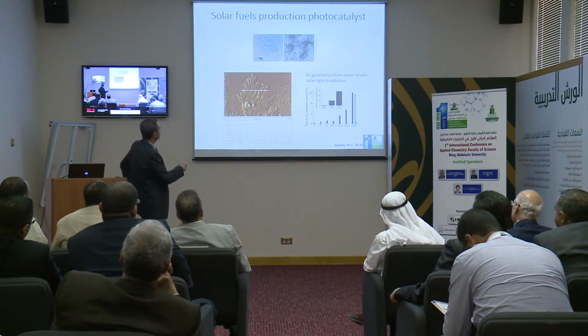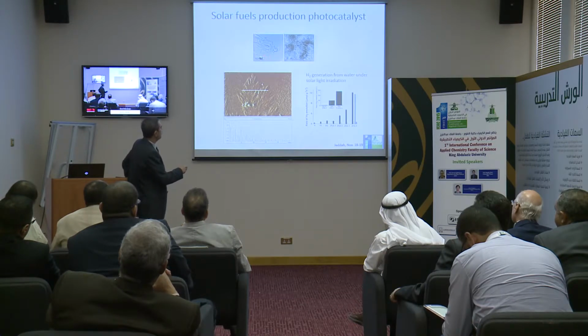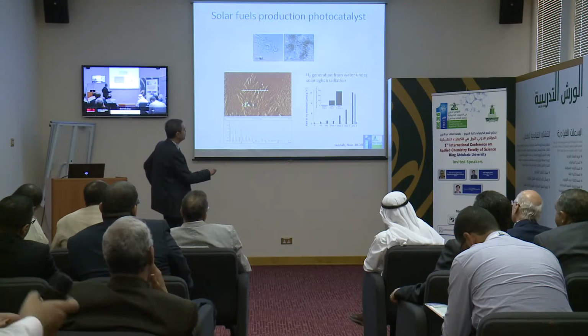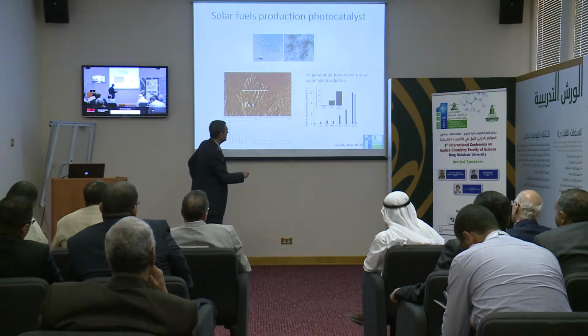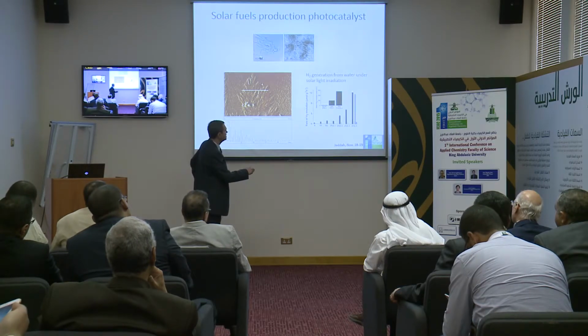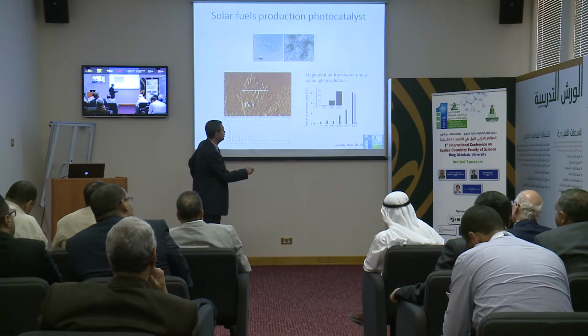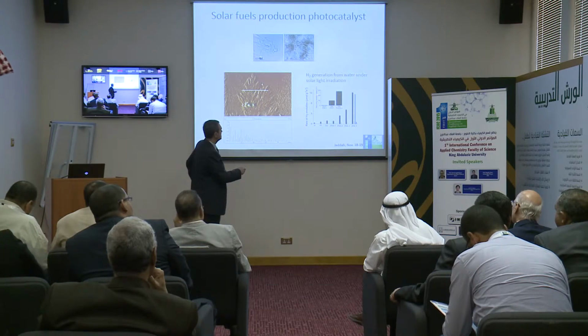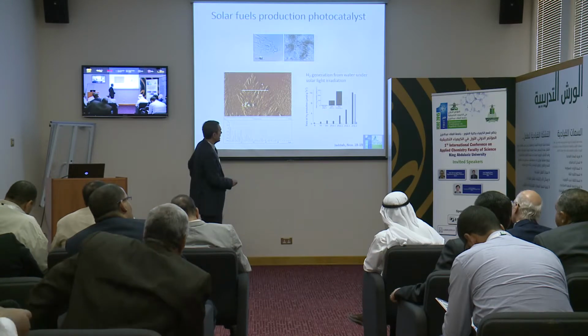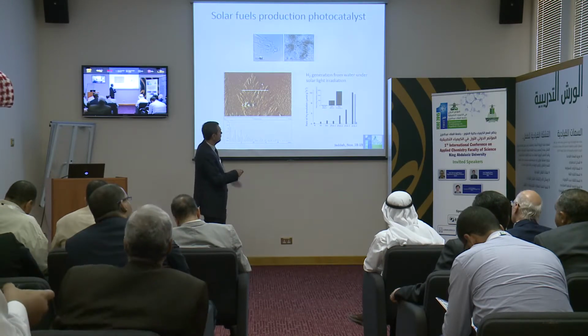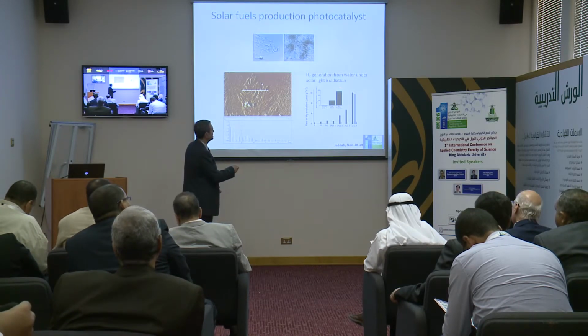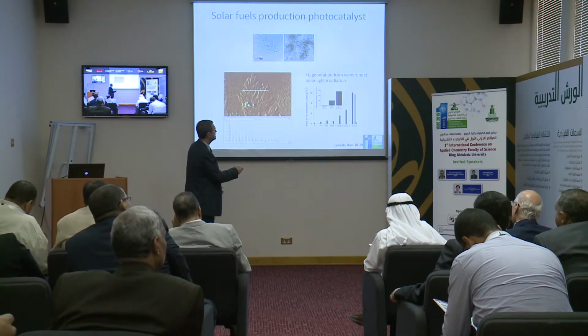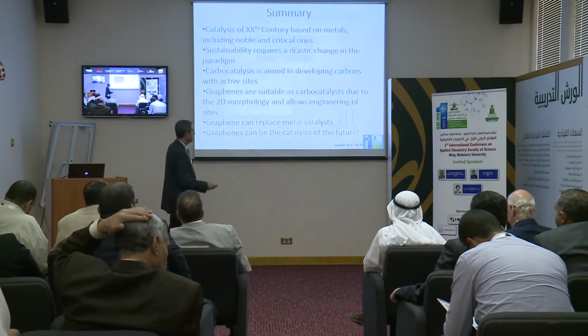These are the images of the phosphorus doped graphene, and we have used this for hydrogen generation from water using solar light. And this is the hydrogen generation. This is the first use, and this is the reuse of the material. And this is the micromoles per gram and per hour that we are able to generate. And of course, if we put some platinum, then the activity increases, and then what we have is 300 micromoles of hydrogen per gram.